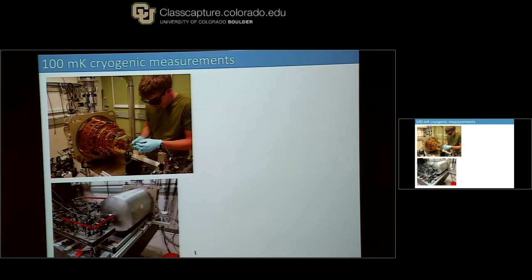And that Tc can be important because the biggest question in all of this is, for any device you might want to do this with, you're going to be putting a lot of optical photons in, depending on how large your coupling is to the mechanical system. Those optical photons will scatter at some small level, but any optical photons hitting the superconductor can be a problem. And the higher the Tc of that thin film, probably the better.